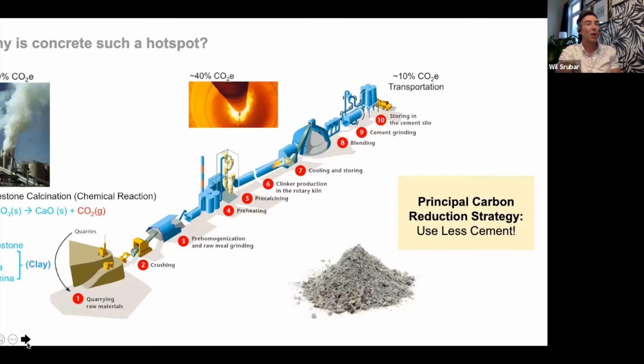As we continue to heat the limestone and the clay together, you can kind of see further down the process line that another 40% of the carbon emissions comes from the fuel combustion that is necessary to heat the kiln. And as we go further down the process, as we start to blend it and grind the cement, and ultimately transport it to ready-mix plants, that about 10% of the carbon emissions are associated with transportation. So if you think about decarbonization of the electric grid, we can probably address about 50% of the carbon emissions with better fuels, renewables integration, with fuel combustion and transportation, switching to renewable energy sources.